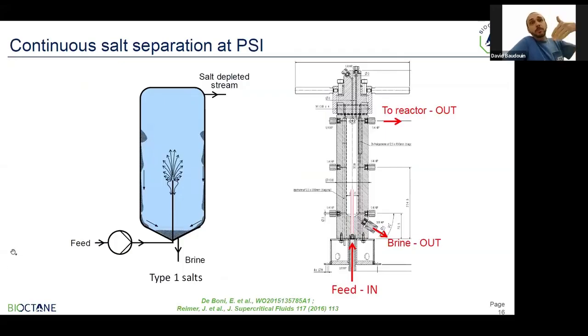This is actually an advantage because we can use this property to separate the salts from the mainstream. That has the advantage of protecting the catalysts that will be downstream of this separation step from clogging. Here I show you, on the left, a very schematic scheme of a separation vessel that was designed at PSI, and on the right is a more technical one. The concept here is that the feed is fed in from the bottom, and as it goes up in the separation vessel, the temperature rises very quickly. Once reaching the critical point, the saturation point, the salts separate and precipitate or form a liquid brine that falls to the bottom of the vessel by gravity, and can be extracted continuously or semi-continuously. At the top of the vessel, the main stream comes out and it's salt-depleted.